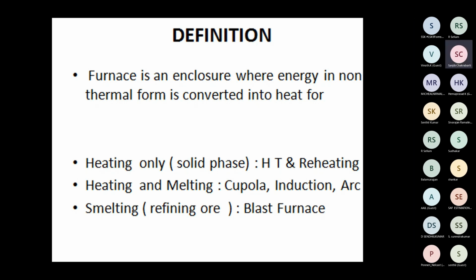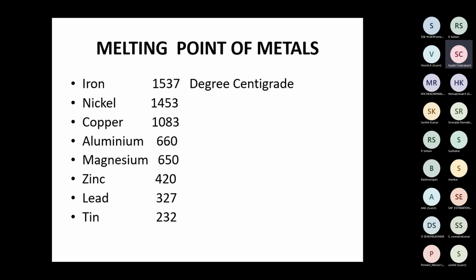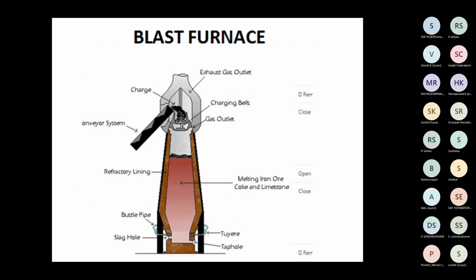So these are the melting furnaces. I have shown you the cupola. This is my area of interest, many of the things, and the charging. You will see the color inside is different. The upper side is a reddish color because the temperature is less. On the lower side, the emission or radiation is different. From the radiation pyrometry point of view, the lower side is whitish because the temperature is very high. In the lower zone where the hot metal is, the most severe conditions are faced by the refractory.